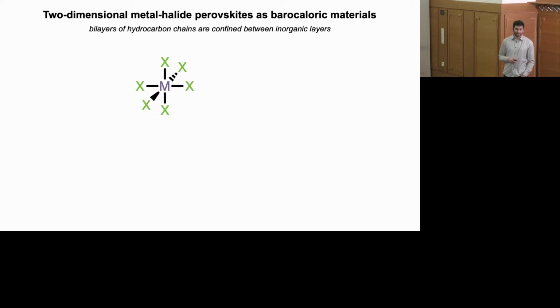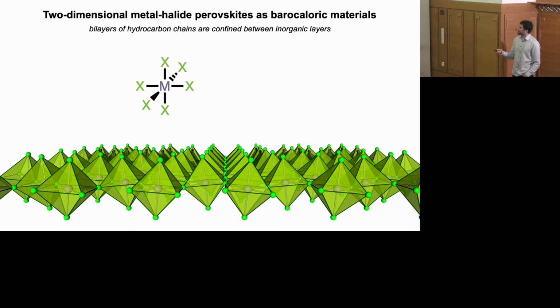These contain octahedral transition metal centers that are typically coordinated to 6 halide anions. These form infinite two-dimensional sheets, such as the one shown here, where you have corner-sharing halides that connect all these different metal cations together. In these two-dimensional sheets, you have a divalent metal cation and 6 monoanionic halide ions, so these sheets are negatively charged. You have these negatively charged pockets between all of these different axial halides, and these pockets can accommodate different organic cations. For example, the alkyl ammonium cation that I'm showing here can sit right in the center of these pockets.